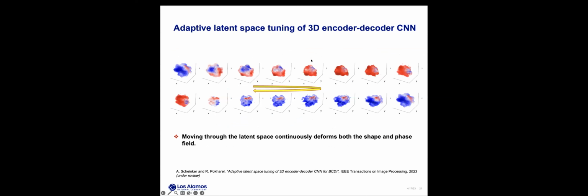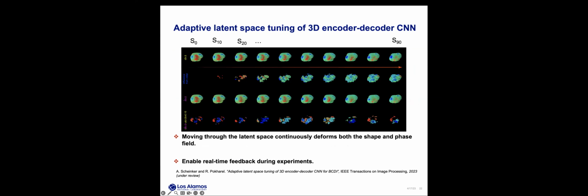So here's just an example where we're starting with this 3D grain and moving through this latent space. You can continuously deform both the shapes and the phase field inside these crystals. And here's an example showing the ES algorithm tracking the electron density of this time-varying state of this object based only on a continuous match of the measured CDI intensities.